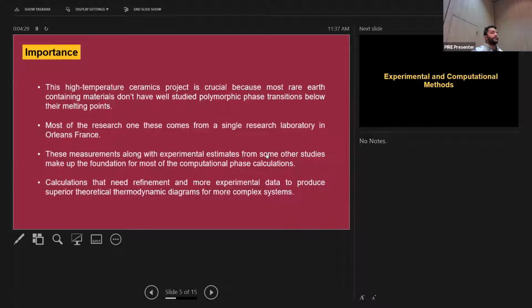fail prematurely, which brings us to the importance of this research project, which is crucial because most rare earth containing materials don't have well-studied phase transitions below their melting points. Like I said, their melting points are close to around 2,000 degrees C, and equipment needs to be specialized in order to actually get this thermal information. Most of the research on this, as I said before, comes from a single research laboratory in Orleans, France, and they published their articles around the 60s and the 70s.